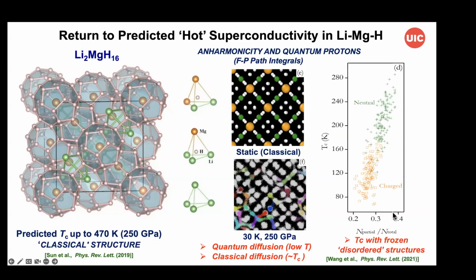So if you basically just freeze these structures and calculate the TC in a rather crude sense, make some assumptions for the charge on the hydrogen, you see a whole range of TCs that start at basically above 400 Kelvin for the calculation in the absence of any kind of diffusive or anharmonic motion or quantum effects, but going down to very low temperatures. So a range of TCs, and this just points out the need to go beyond the conventional theory and take into account at a fundamental level the nature of basically both the anharmonicity and the quantum effects in the system when calculating TC.